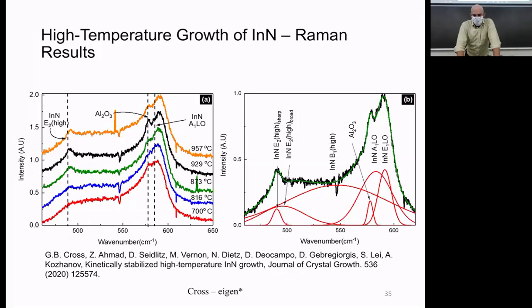The issue that we have, though, is that when we look at breaking this curve down into understanding what it is, we have to figure out what's going on. And we have two peaks that are actually related to the structure of this material. There is a broad peak. You can see this long, low, broad peak that is present in all of the samples. And in some of the samples, we start to see a second higher sharp peak. And that doesn't exactly bode well for my material, but it's not a killer strike yet.